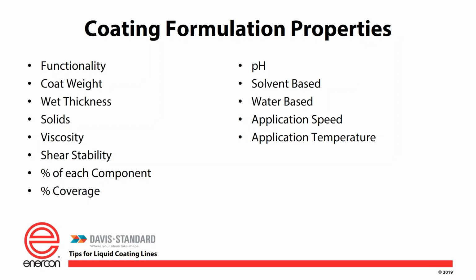Viscosities. Viscosity is a measurement of the flow of the liquid. So if you're running a viscosity like water, which would be about a 1 centipoise, a reverse roll coater would have a pond on it or a fountain feed or a pan feed. If it's water, I can't use a pond because it'll fall right through the gap. A higher viscosity, something like a syrup or a motor oil type viscosity, something a few hundred to 1,000 centipoise, you would run with a pond fed between a gap.